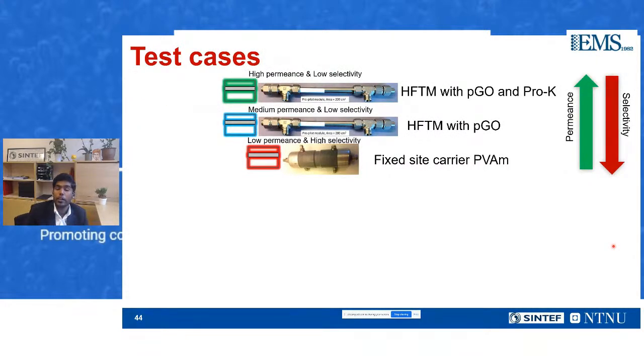For this system, we also chose 3 different membranes. One was the membrane which contains porous graphene oxide and the mobile carrier, which is of high permeance. Second one was the membrane with high permeance as well, with porous graphene oxide. Both of them have very high permeances and lower selectivity with respect to the third membrane, which we chose, which is a fixed site carrier that was developed earlier in the group of NTNU, which contains polyvinylamine, and that has a very high selectivity, but on the other hand, very low permeance.